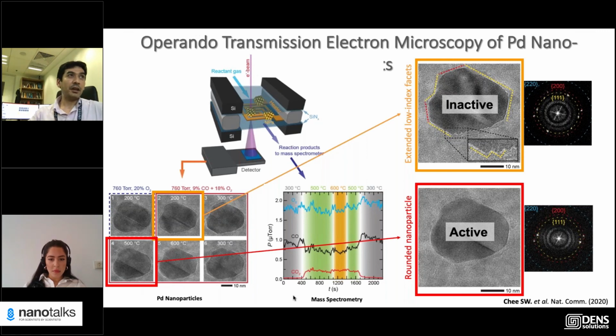So that particular one, palladium oxide does form on the surface, but that particular one is not. It's kind of amorphous, so we think it might be just CO building up. Palladium oxide does form on the surface during the reaction, but it does not change. So in a very few particles we can identify it just from the lattice fringes when it's a crystal oxide. We can identify that it is a palladium oxide.